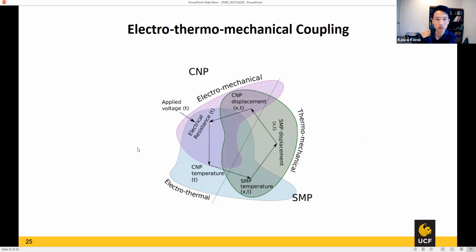So the problem really is a coupling between the electromechanical behavior, the thermomechanical behavior, and the electrothermal behavior, right? So you have the carbon nanotubes that would heat up, that would have heat conducted to the shape memory polymer, which can then change shape. That shape converts to some amount of strain that is going to be registered by the CNP. And based on that strain knowledge, one can go ahead and try to control that shape by modulating the temperature. So this is the overall idea we have.